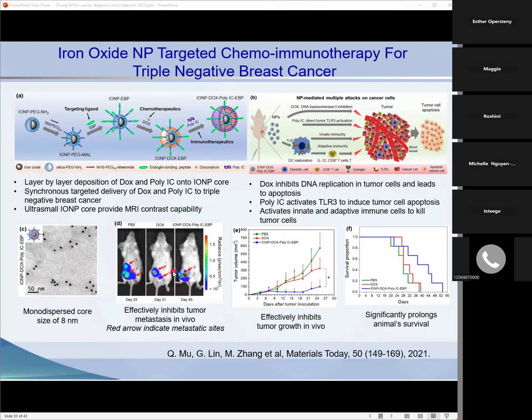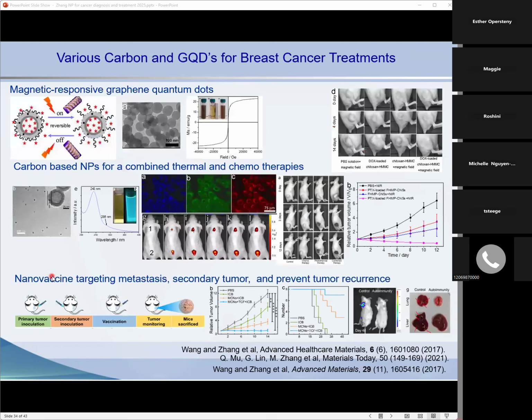combined chemo and immunotherapy. This is one example of a nanoparticle made layer by layer. This is an iron oxide nanoparticle with negative charge. Then we placed a particular ligand that can target the triple negative breast cancer. Then we coated it with positively charged doxorubicin, and then also with negatively charged poly-IC. So this is a very compact, simple nanoparticle. We found that these nanoparticles, of very small size, can really inhibit the metastasis, reduce the volume, and increase the survival.